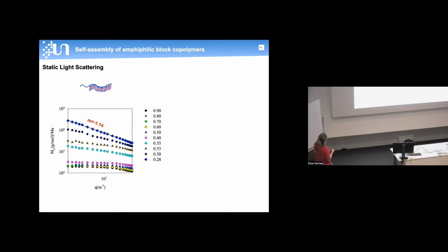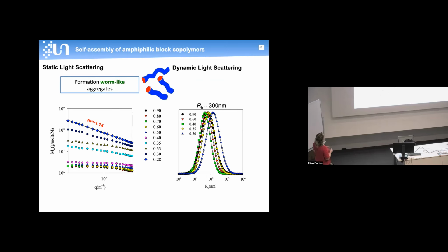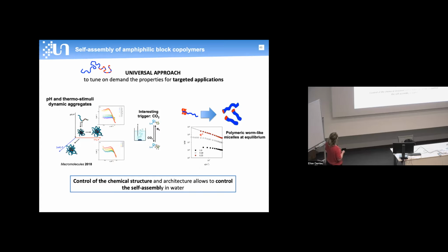here represented in this graph, we could see that there is a dependence in Q^-1 at a low ionization degree, which is representing worm-like aggregates, and which was confirmed by the size that we could measure by dynamic light scattering. So we still have to go on this result to really show these worm-like aggregates using this bottle brush copolymer.